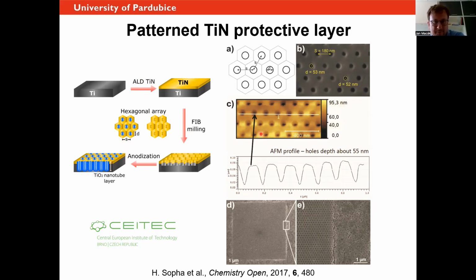And then we anodized it, using the pre-drilled holes. And it was actually amazing to see how the holes were perfect, first of all. And second, how this area, which was patterned, really remained in the same patterned way also underneath the titanium nitride layer. So here is the interface of pattern on patterned surface, and you can see the huge difference.